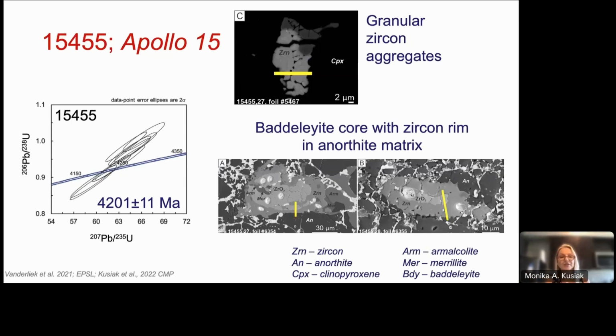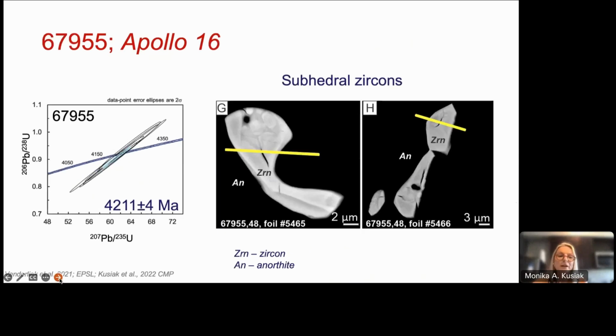young. And here in this sample 15455, we have two types of zircon. We had granular zircon aggregate, this one at the top, and we had two grains where zircon was a rim around the baddeleyite, and all these were in anorthite matrix. And the yellow lines are where the FIB foils were cut for TEM studies. So these tiny areas across the zircon were cut.